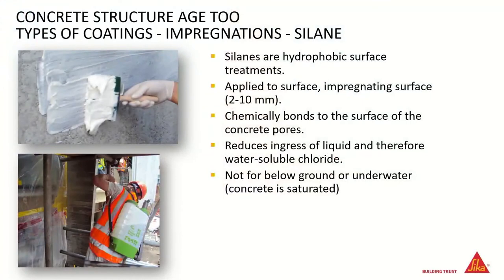Silanes are hydrophobic surface treatments. You apply them to the surface, and depending on your application and the location, you might choose a different type of makeup. This top one is the cream type. It's applied quite easily, and you would use that where, say, you have a high wind environment. If you've got a lot of wind and a lot of drying action, you'd use something like that because you don't want the product that's supposed to be going onto the surface being blown away. You'd also use the cream type where access is quite tricky, or you need to apply in a short period of time.